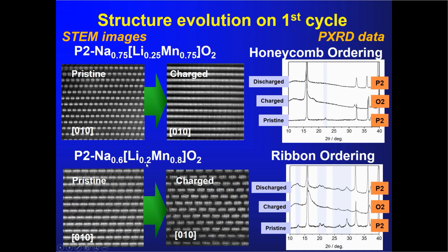In the case of this slightly different composition with the ribbon structure, you see a different arrangement here of these sort of four, not a dumbbell now, but these four dot features which are associated with the ribbon structure. This ribbon structure remains on charge and on discharge. And here's the powder diffraction pattern. Here's the pristine material, then on charge. These peaks appear to disappear, but they reappear on discharge. So it isn't that the structure is completely, if you like, immobile, but it's reversible. The structural changes that happen are much smaller, and they're reversible. You come back to the same arrangement on discharge, as indeed you have to, of course, if the voltage curve does the same thing.